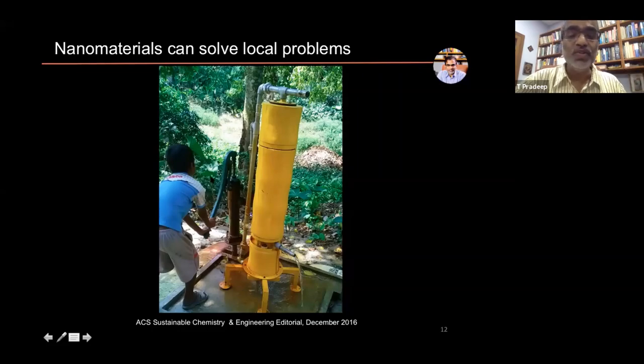And because you can make new materials, because you understand their science better, you can put such materials into a small box and construct a device like this. With one stroke, this boy gets 300 ml of clean water without arsenic, and this pump of course can be used for 1,000 liters of water a day. And just with this much of material, about 7 kilograms, you can get clean water for about 1.5 years. That is impossible with any other material other than this kind of nanomaterials.